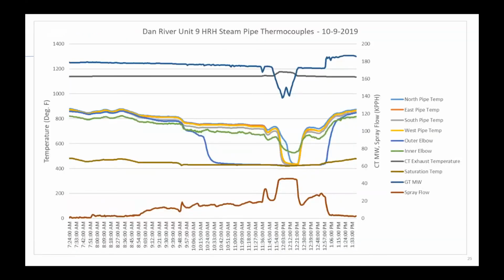So this was a plot showing those thermocouples I mentioned that we installed on the steam piping, and this was before the steam atomizing Attemperator was installed. So this is the original spring-loaded nozzles. The thing that I was kind of keyed in on in this plot was the difference in temperature between the outer elbow, which is the darker blue, and then the inner elbow, which is the green color. And you can see when that outer elbow gets quenched, the unevaporated spray is going to the outside of the elbow just from the force of taking that turn. So you see that outer elbow go to saturation, and the inner elbow is hanging up there around 700 degrees or so. So you got about a 300 degree differential across that elbow.